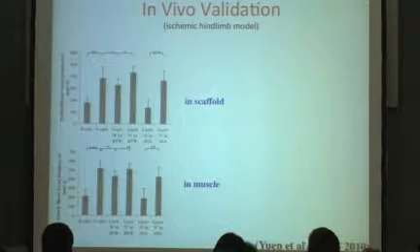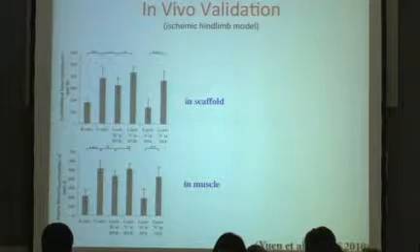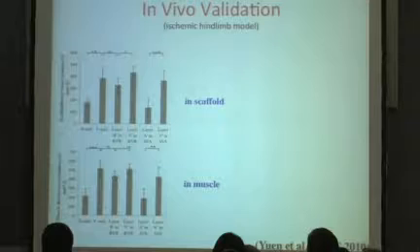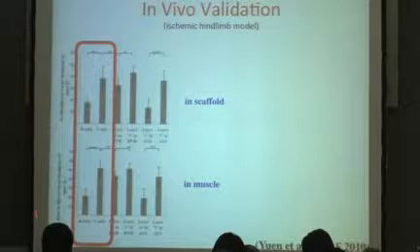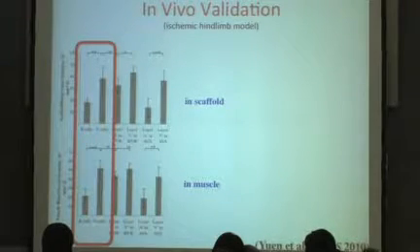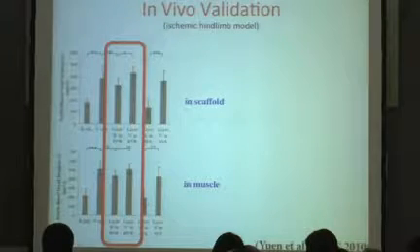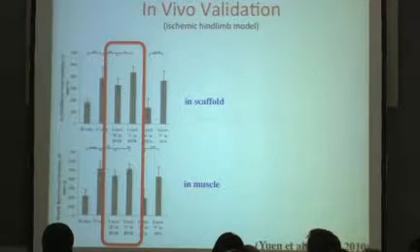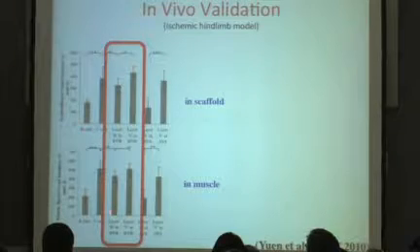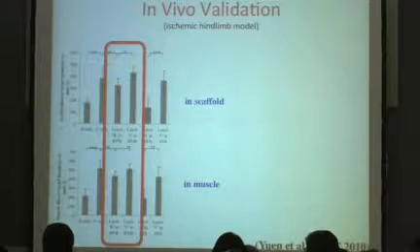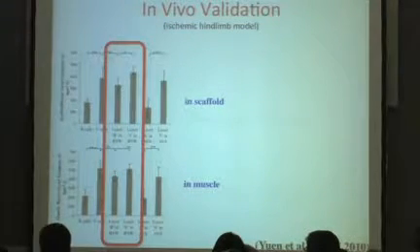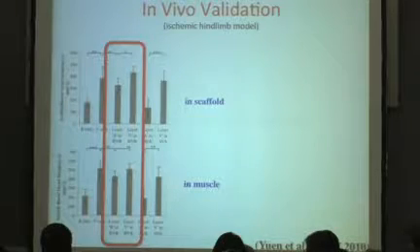And I'll just give you a piece of data here to document that this is indeed something that can happen. So we went back again to the ischemic hind limb model. If we first of all look at this bar, we'll look at, let's say, the capillary density in the muscle. When we deliver VEGF, as I described before, from the polymers, we get a significant density of capillaries that gets built up as compared to doing nothing. However, what I didn't describe before is if we look adjacent to the region where we put this polymer, at some distance away, you get a really large spillover effect, which oftentimes may be useful. But in this case, it would not be desirable. So you get a lot of VEGF activity and a lot of angiogenesis, even in the adjacent regions.